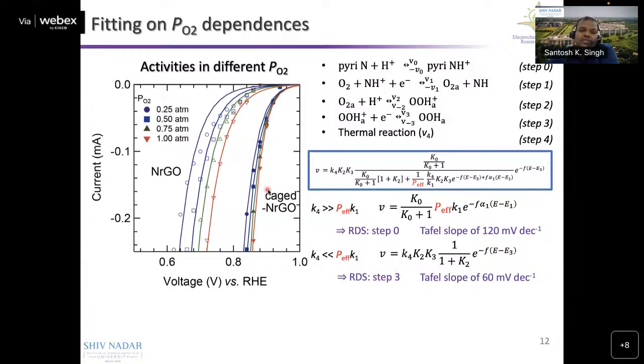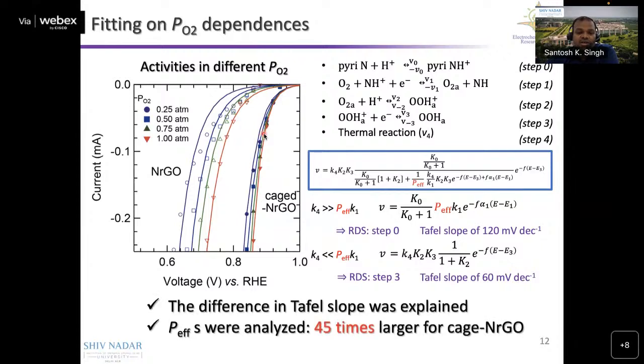As I said, if oxygen is captured in the hydrophobic case, how does it affect the catalytic activity? The partial pressure effect has shown that the hydrophobic caged catalyst has almost 45 times higher partial pressure of oxygen in the catalyst, which means that it is continuously supplying oxygen to the catalytic active sites, and the catalyst keeps running without being affected by the hydration of water.